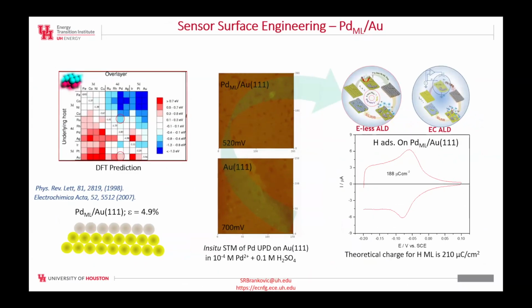Now, typically we can coat the fiber Bragg grating with gold, and we can put the palladium monolayer, which is super sensitive to hydrogen adsorption. We are a well-known group who developed all these fancy methods to deposit and control monolayer deposition. Here, I just give you an example of how sensitive a palladium monolayer is to hydrogen adsorption. We can measure exactly a monolayer of hydrogen adsorbed on a palladium monolayer on gold. Therefore, if I have a gold-coated fiber and we put just a palladium monolayer, that would be just about a perfect sensor for hydrogen.